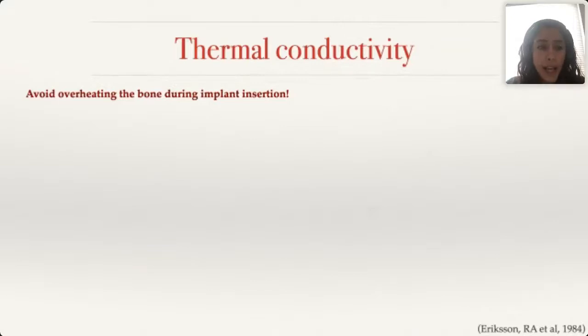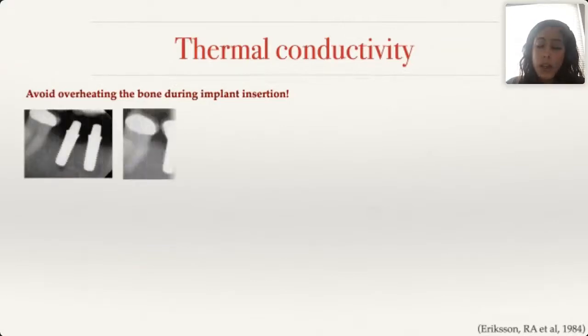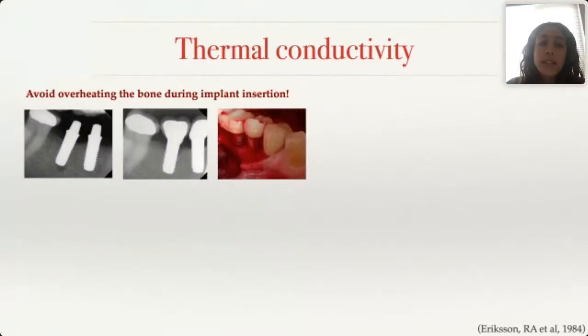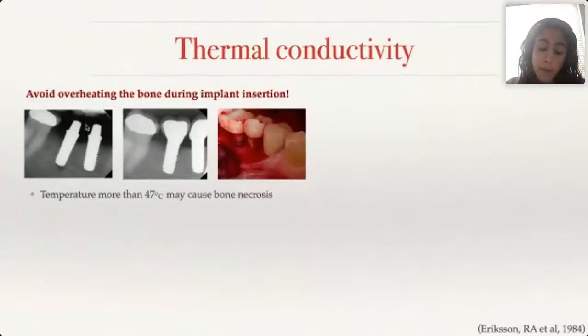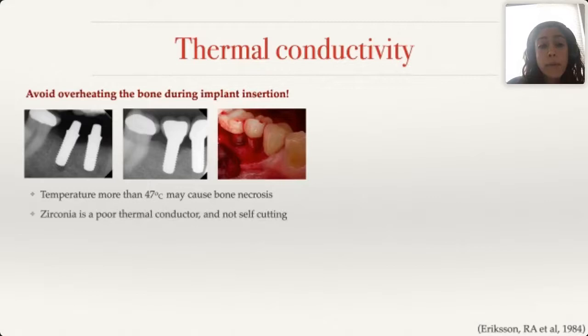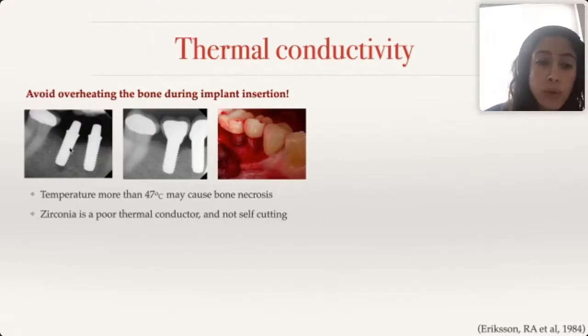That's very important to understand because when we place these implants, we don't overheat the bone, because zirconia is not a conductor of heat. During placement, if we apply too much torque, we can produce a higher temperature than the recommended threshold of 47 degrees Celsius. Above that, we get bone necrosis. This heat is not absorbed by the implant, it's sent out into the bone, and we end up overheating it.